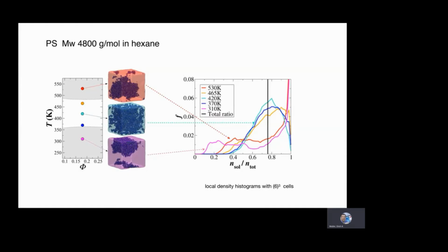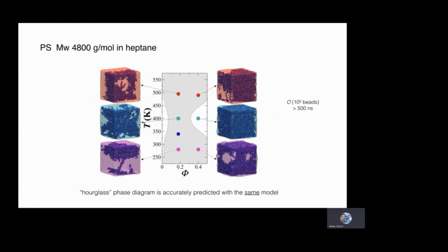However, for the top and the bottom, it's evident that the system looks like it's in a two-phase system. And by looking at the histograms, we of course see that there are two peaks, one peak corresponding to the pure solvent and another peak that corresponds to the polymer phase. An interesting result is that if we change the solvent from hexane to heptane, instead of finding this upper and lower solution temperature type diagram, we find what is called an hourglass diagram, in which we have regions of volumetric fraction for which there is always a phase separation, but some others where there is a change between a two-phase system and a one-phase system.